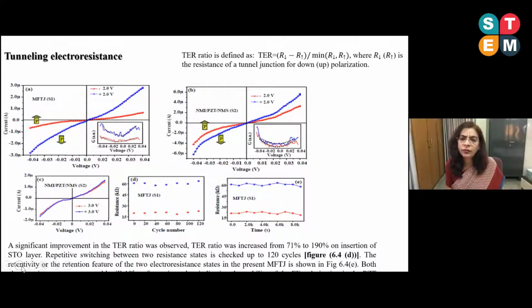In this case, the dielectric layer, strontium titanate, was removed, and we were able to see the change, but it wasn't as prominent as here. So we believe that this dielectric layer tries to improve the interfacial characteristics and plays a major role in this device for giving a large change in the TER value.